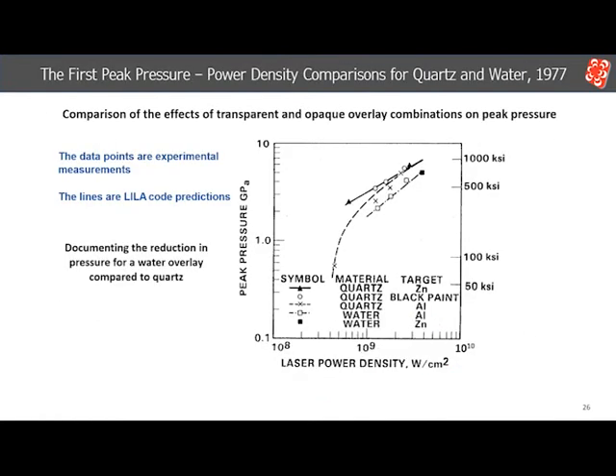This is the compilation of peak pressure dependence on power density gathered over the previous 4 years. The data points are the experimental measurements, and the lines are the LILA computed results. There's very good agreement. Because the measurements covered included the lower range of power density, down to 4 times 10 to the 8th watts per centimeter squared, we see lower pressures from the aluminum surface than the zinc. This was attributed to its high thermal conductivity, increasing the energy lost from the expanding vapor by heat conducted into the substrate. Above 1 to 2 watts per centimeter squared, this energy loss becomes small relative to the applied energy, and it aligns with the zinc and black paint data.